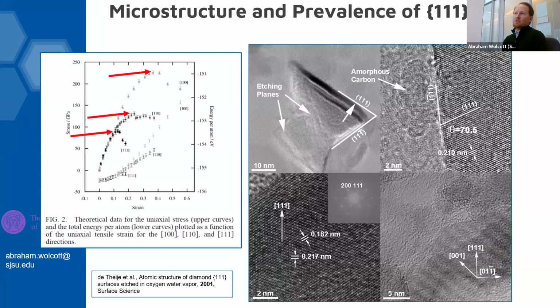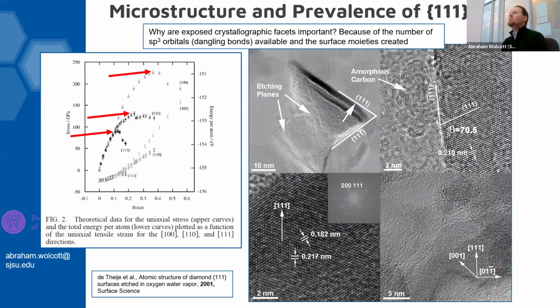And the answer has been known for hundreds of years by jewelers, but has recently been described by DFT. In this particular figure, we've got strain versus stress. We add strain to our diamond, and then eventually it fails due to the stress, and we have cleavage. First, it's the 111, then it's the 110, and then the 100. So during the ball milling process of macroscopic diamond, to make HPHT nanodiamonds, we're basically following the preferential cleavage of diamond in real time. But why do we care?